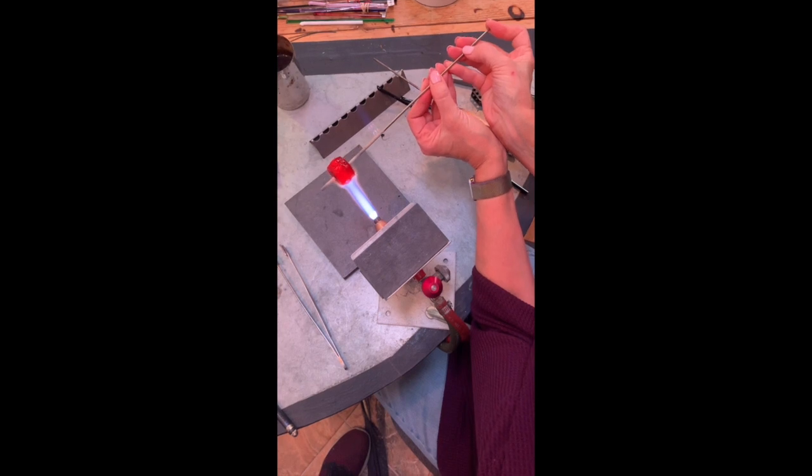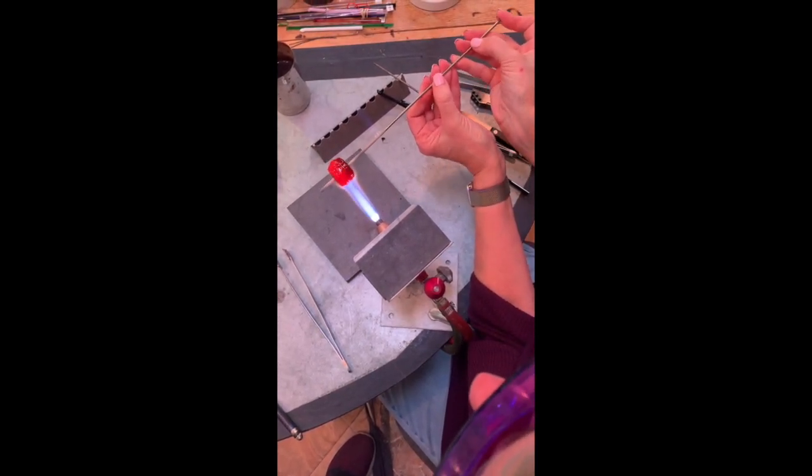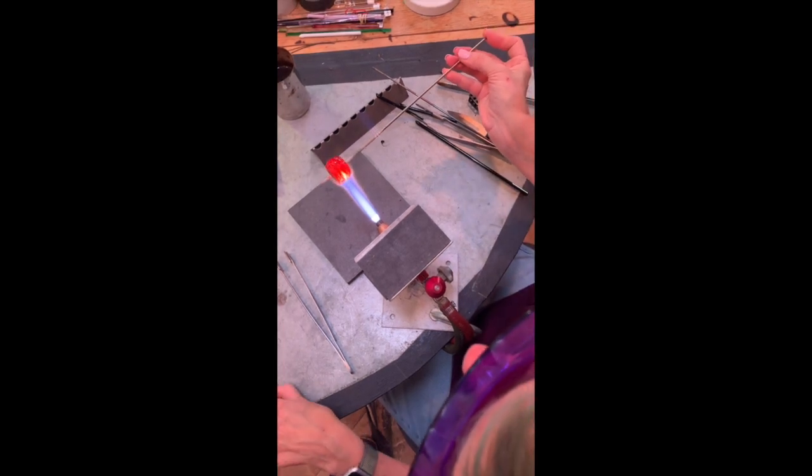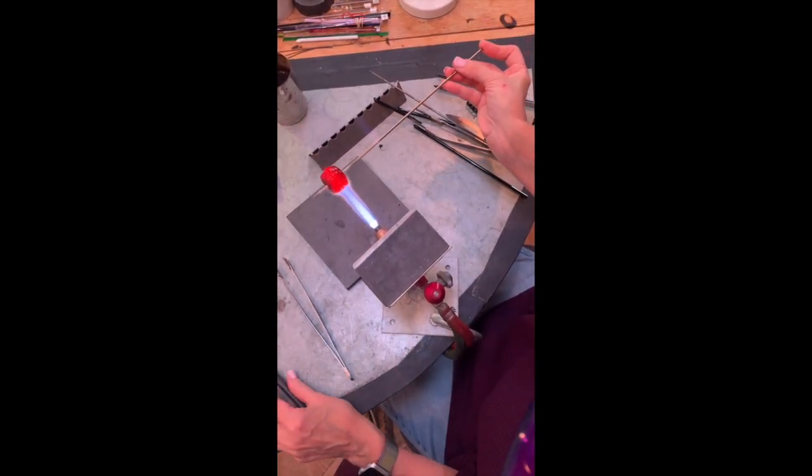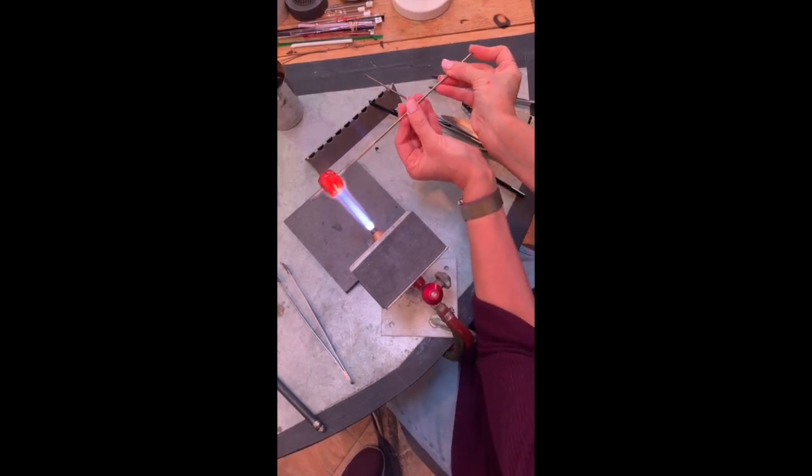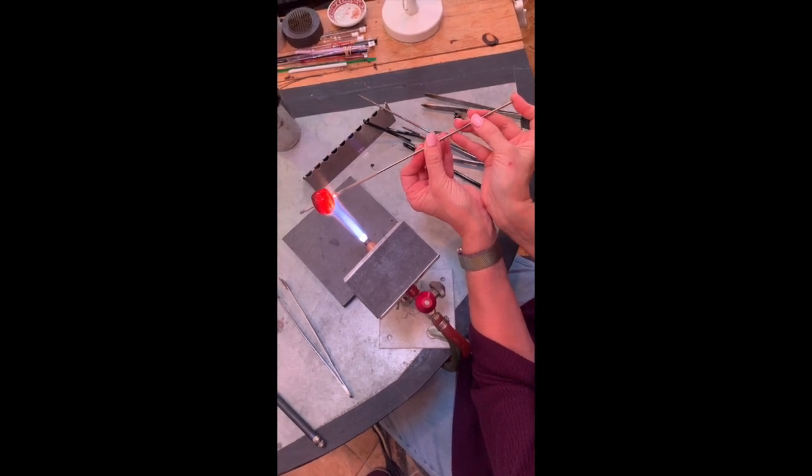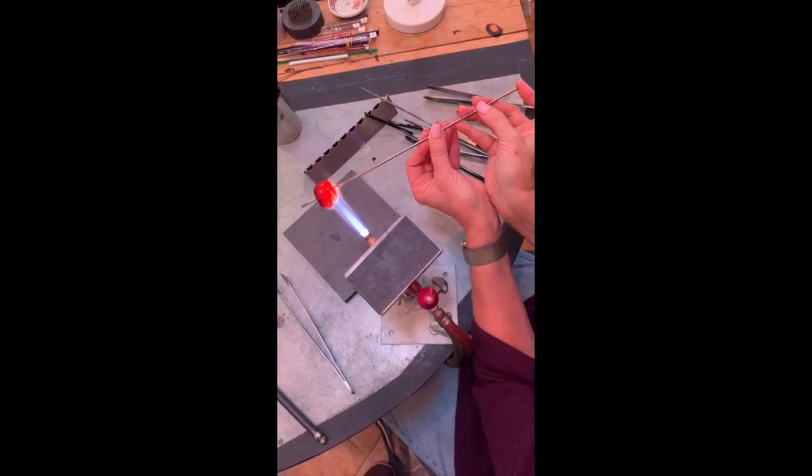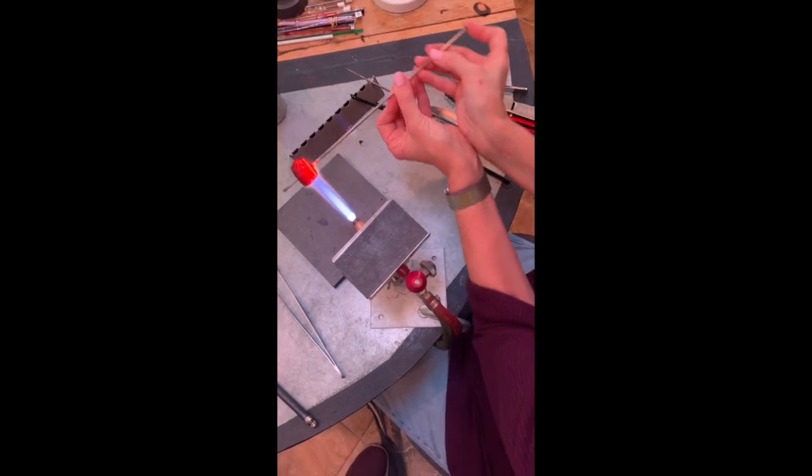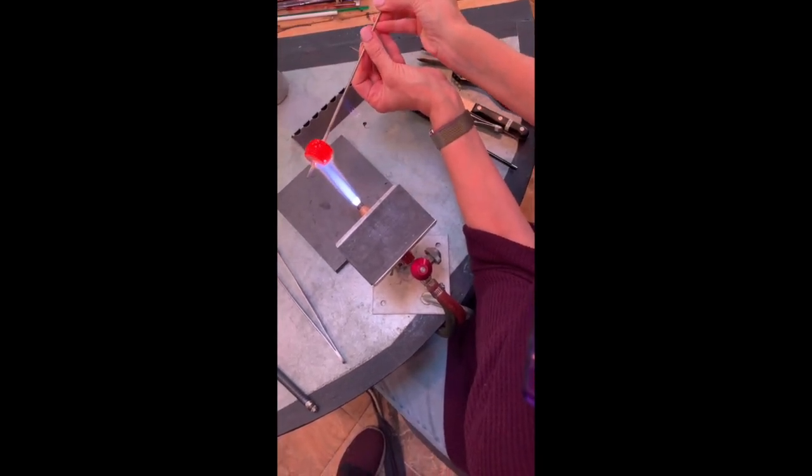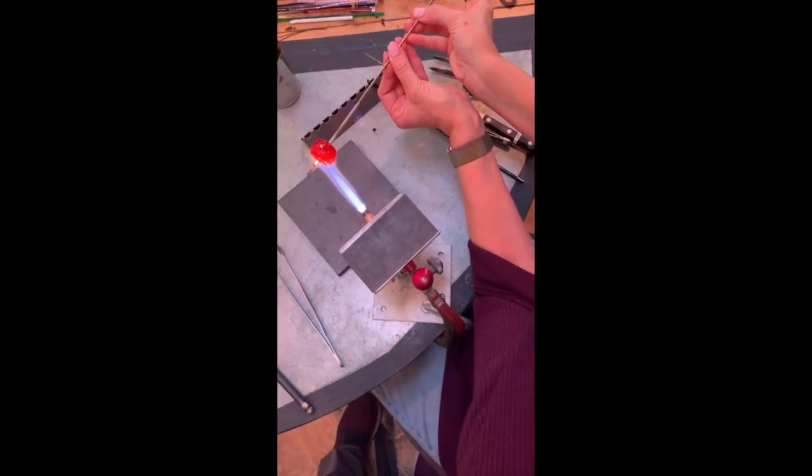I want you to just get the basics down for now. So what I'm doing is heating the bead. I see one little spot there where I think maybe there's an opening. I'm just moving the glass over. Remember, I want to avoid adding extra glass if I can, because it just makes a heavy spot. Again, when we get to troubleshooting, if your bead doesn't inflate evenly, one of the reasons could be that your walls are not of an equal thickness.